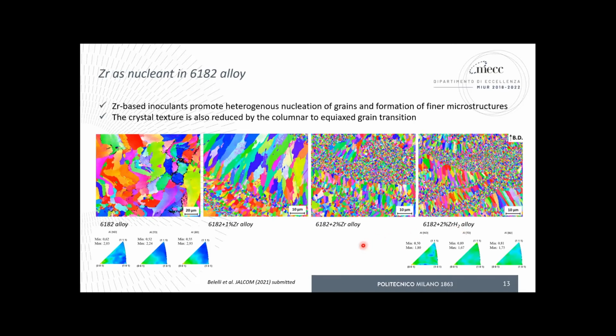One additional point we can mention is that there is also an effect on the texture. Actually, the texture of the original alloy was not that sharp, but at least we can claim that by comparing the standard alloy with the zirconium-modified alloy, there is a smoothing down of the texture. We can get a more homogeneous crystal orientation distribution, at least.